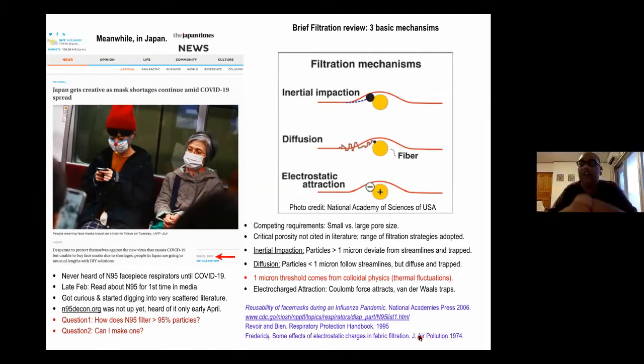And according to that reference, the first fabrics were basically cotton or wool, natural fibers that were triboelectrically charged. That means they took two dissimilar fabrics and rubbed them together to induce charges. And then over time, they started adding resins to them to improve the electrostatic charge retention. But it became a problem because these resins could not work against oil-based aerosol droplets, which can screen charges.